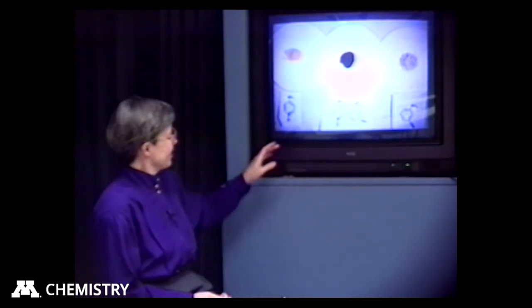But the reaction goes very quickly. After 3 or 4 minutes, you see a slight red change if you just keep grinding and grinding. And if you grind nice and hard, after 5 or 10 minutes, it will be this really, really deep red color. So this is a good example if you don't believe me. Good one to try yourself.